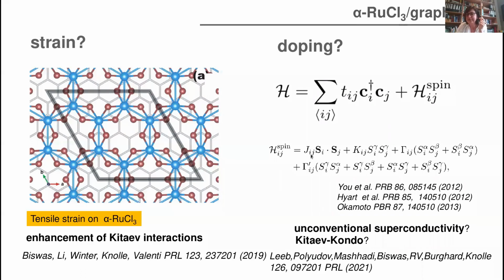What we want instead is interactions between the ruthenium atoms that go through the chlorine. That means we need to put the ruthenium atoms at a certain distance. So what we want is to strain the structure in a way that we blow it up. That's why pressure is not a good way of going into this limit, because pressure basically brings the ruthenium atoms closer together and then you spoil Kitaev.